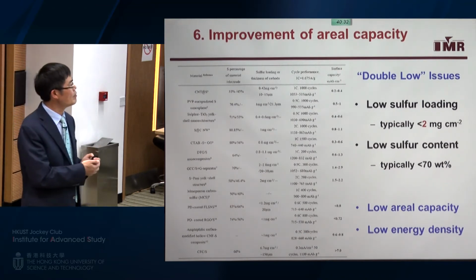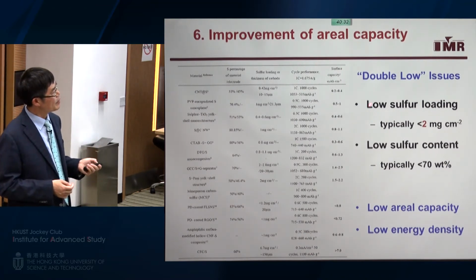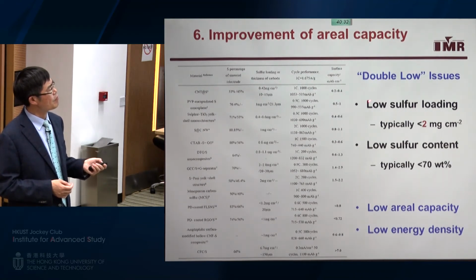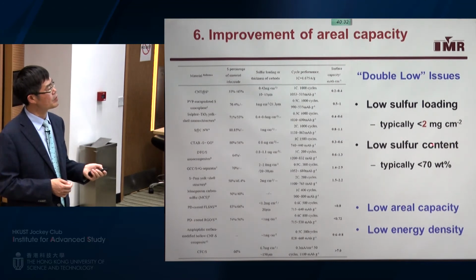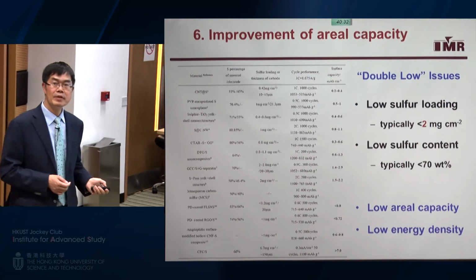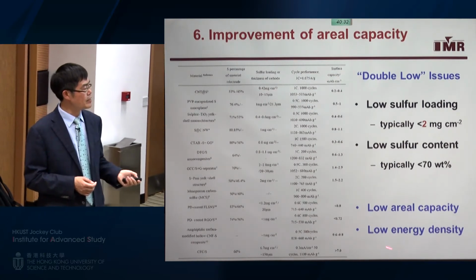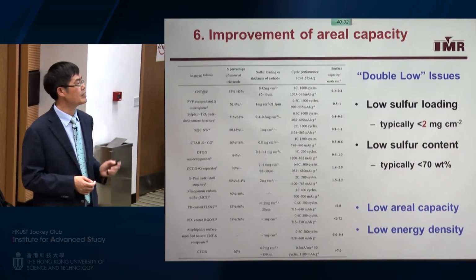And then one more problem is basically for lithium sulfur battery, we only have very low sulfur loading, less than 2 milligrams per square centimeter, and also very low sulfur content, less than 70 weight%. That means very low area capacity and very low energy density.